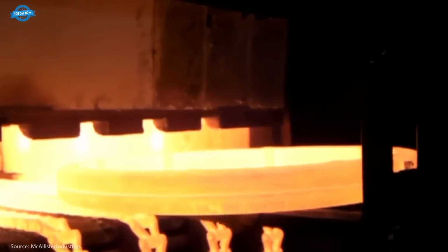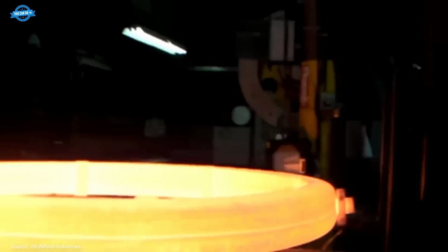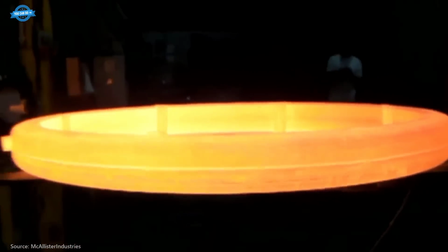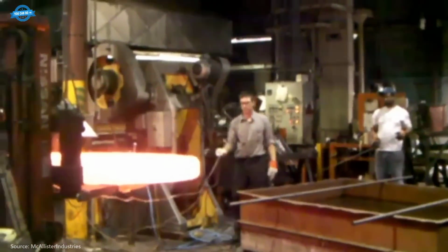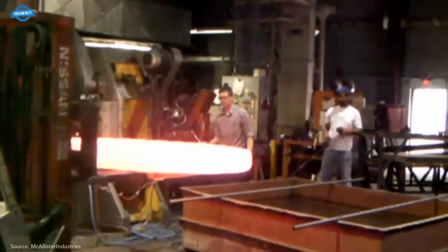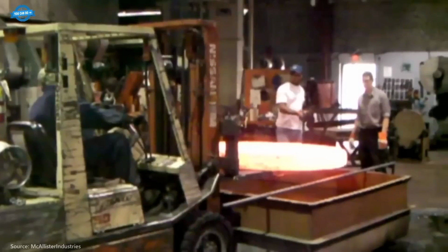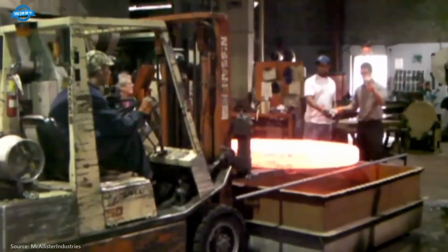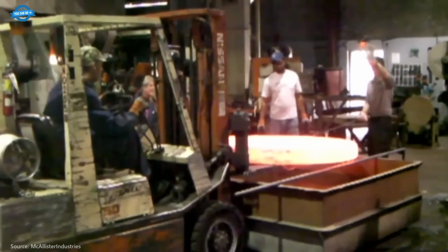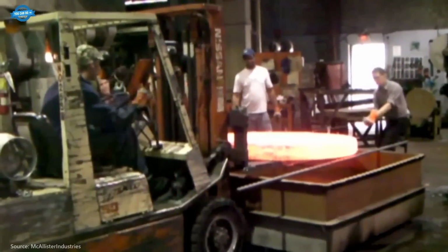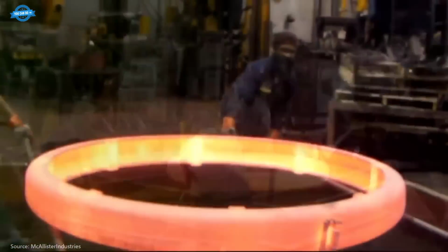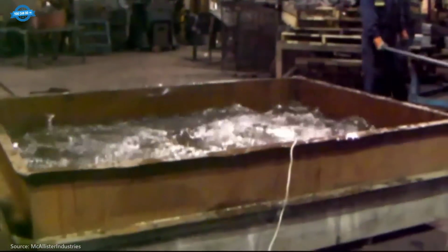Once removed from the furnace, the part is quickly immersed in a quenching tank filled with water to rapidly cool it down. This rapid cooling alters the microstructure of the steel, improving hardness and strength. The entire thermal history, from heating to quenching, is recorded using a portable chart recorder for quality control.